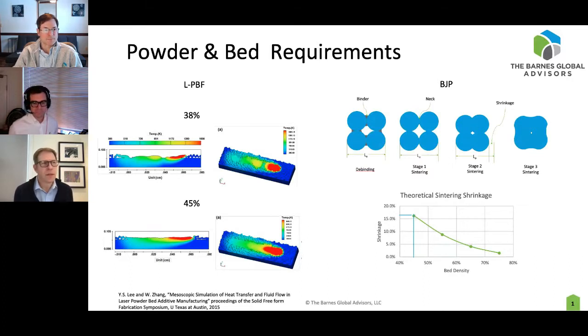And I think you picked up on something there that probably goes unnoticed. I don't hear people talk about it, but binder jetting is a solid state affair. So the microstructure that you start with on the powder is still present in the sintered product, in some way, shape, or form. Whereas in powder bed, since you've remelted it, you've wiped out whatever history was there and you're starting over again. That's right. And this means more to some alloys and their compositional control, phase content, et cetera, than it does in different alloy systems. As a fundamental materials and process engineer, that's pretty cool when you think about the potential implications. It's a little bit like cold spray because you're not going through a melt, so you're able to retain a phase composition.